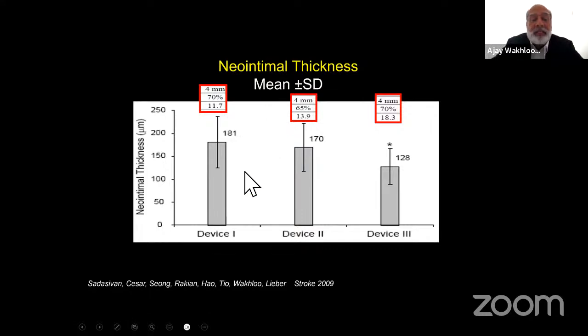As we go more and more distal into smaller vessels, we have to look into that carefully to avoid thromboembolic complications, but also in-stent stenosis. With device one, which had a porosity of 70% but 11 or 12 pores per square millimeter, the thickness of the intima was larger than the device that has finer mesh but the same porosity. And of course, this device, which was intermediate between the two devices, has a mean intimal thickness of 170 microns.